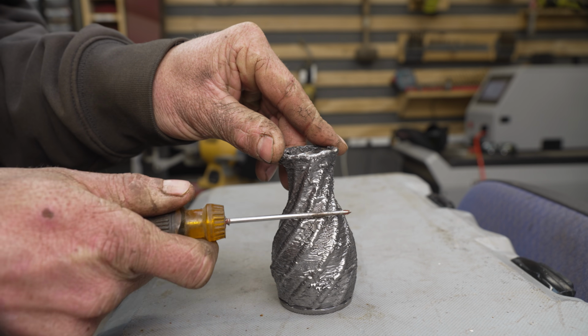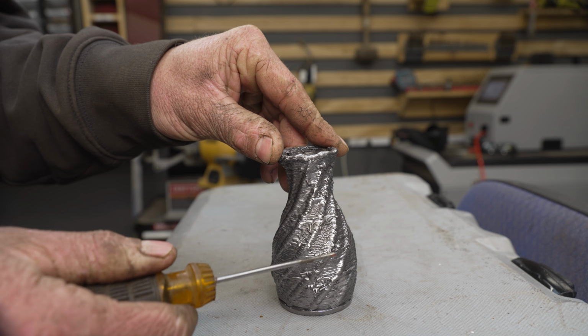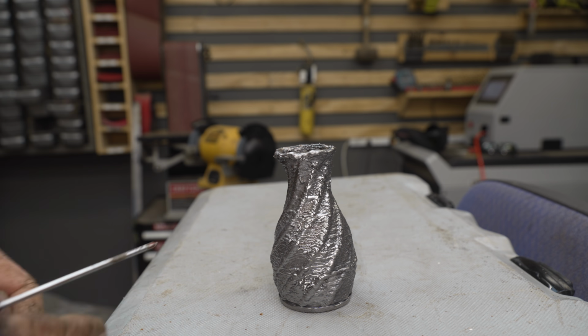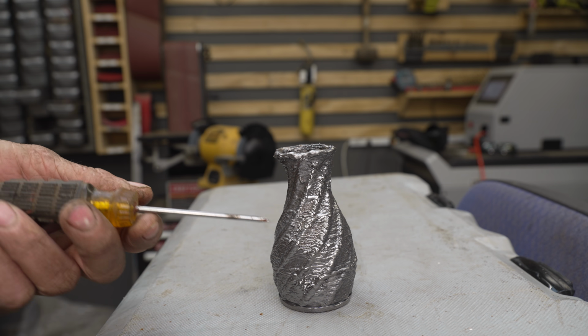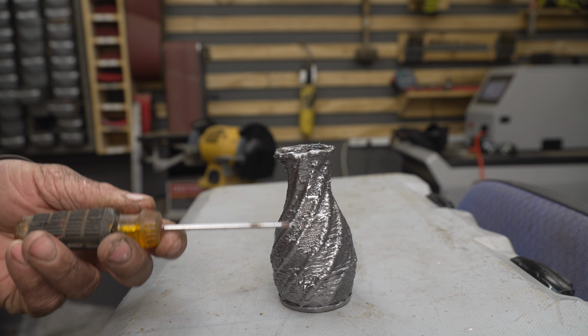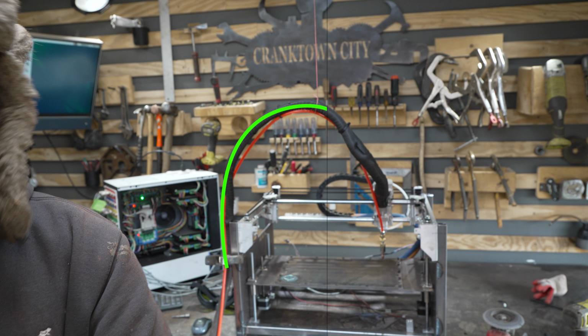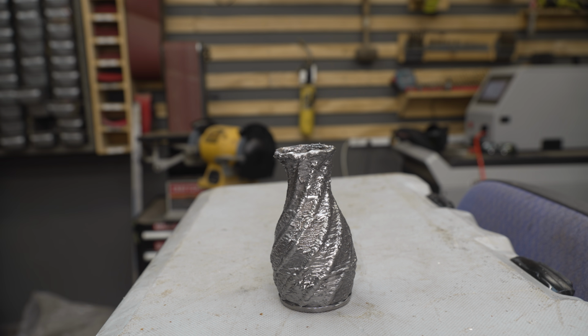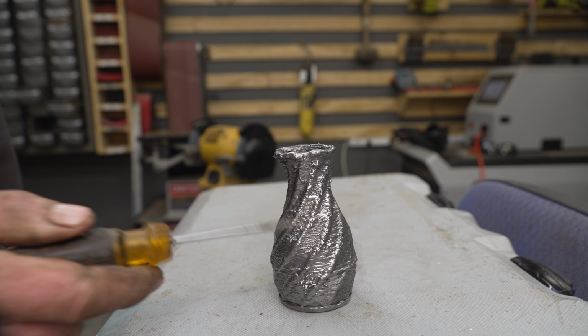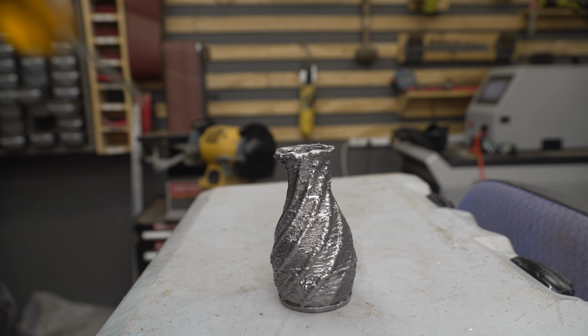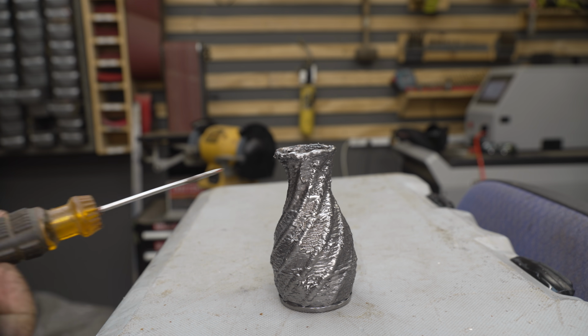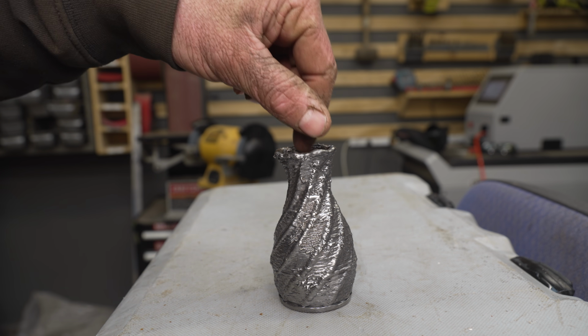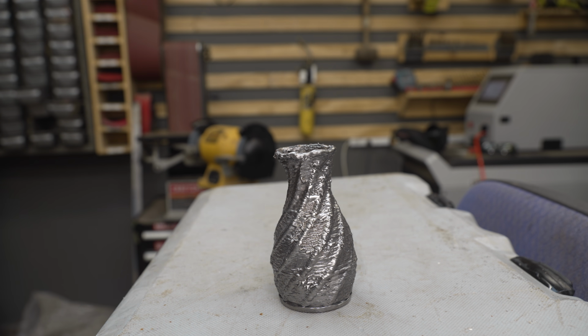This side, that's all rough with all the diddly sticking off of it, is a problem that did not show up beforehand. So I don't know what's up with that, but because of the loop in the wire feed liner, it puts a bit of a bend in the wire and it comes out of the machine at an angle. And this side was on the side that wire was pointing towards. So it was kind of getting stuck on the edge of the puddle and causing little diddlies. But that is very easily fixable. We just got to figure out a better way of routing the liner.